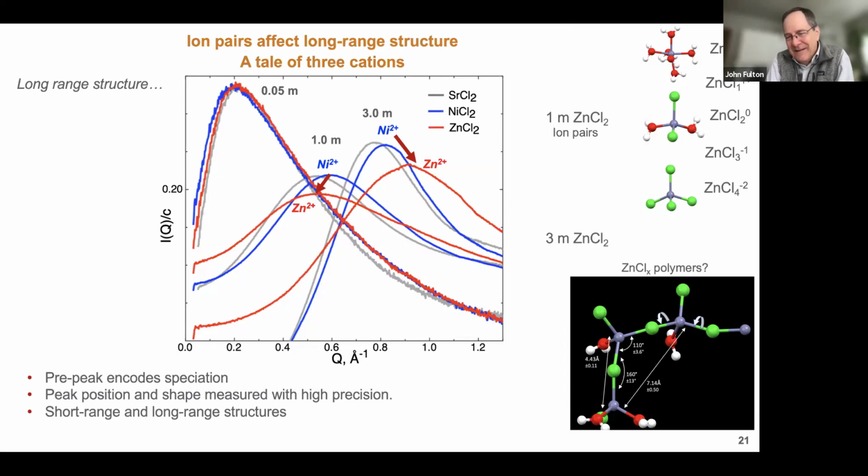Yeah, hi, John. Hi, Tim. This is really beautiful work. We've done similar things with acid-based solutions. And a trick we used to get to the very low concentration pre-peaks was to essentially subtract out the signal from uncoordinated waters. Is that something you've tried? That's what this is. It looked like it, yeah, minus the pure water spectra. So if you're dilute, it's the perfect method. If you're using it at more concentrated solution, then it's not as exact, of course. But yeah, that's our only hope of getting the ion specific signal out of the solution.